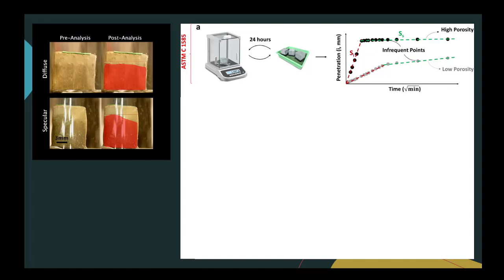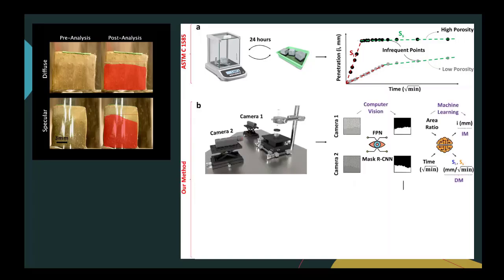And this is another sample, same thing's happening. So my theory is, what if you measure how fast the water level changes, and then use that information to predict the sorption properties? So instead of using the traditional measurement, which is very tedious and time-consuming, imagine you do this test for 7 days. We just place 2 cameras or 1 camera, it's up to you. And then it analyzes the sample, and it captures the area ratio or water level, and then it combines it with the time. So if the change in water level is so fast, that means the material is a bit porous.